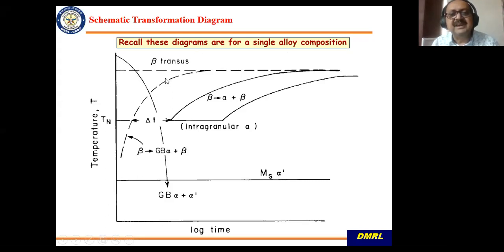That is, you form the grain boundary alpha, and then if you cool it fast enough, you can form martensite in alpha plus beta alloys, but not in beta alloys. I will show what forms in beta. And then you have the precipitation of intragranular alpha, that is the other alpha that precipitates. It can strengthen, it can do other things.